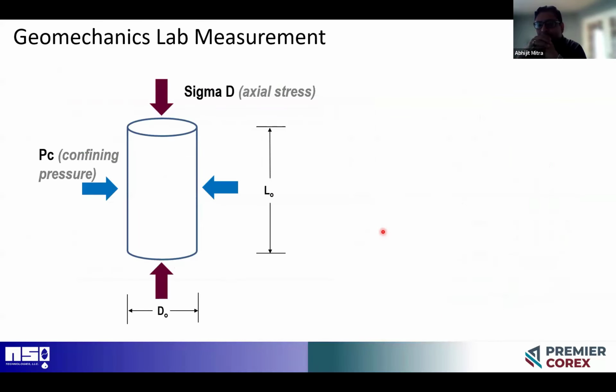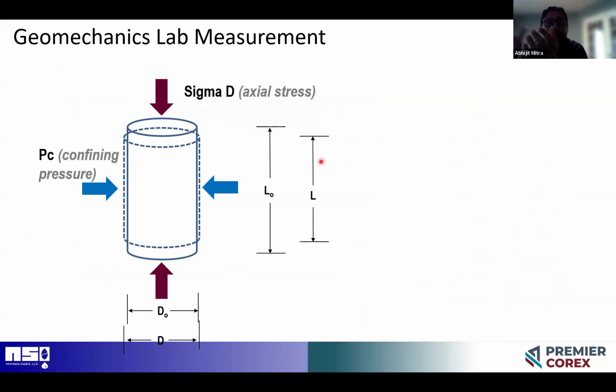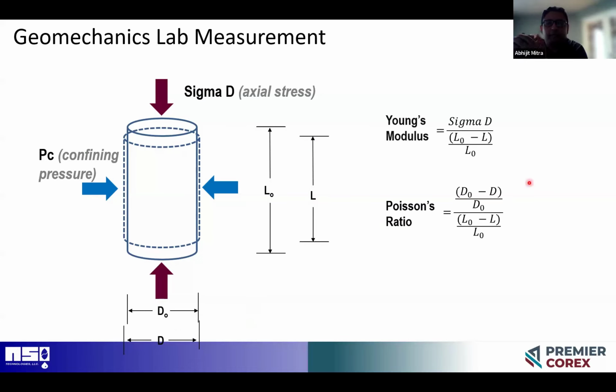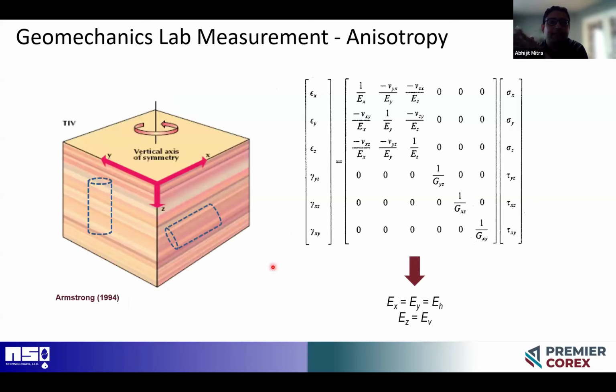The geomechanics measurement that we need to run mostly is what we call the triaxial compressive strength test. What we do here is apply and hold constant stress, which can be equal to the net confining stress, and then we apply the axial load, shown by those pink arrows, at a predetermined rate till the sample fails. During this entire process, we can monitor the change in sample length and sample diameter, which helps us estimate the Young's modulus and the Poisson ratio, which are our static mechanical properties.